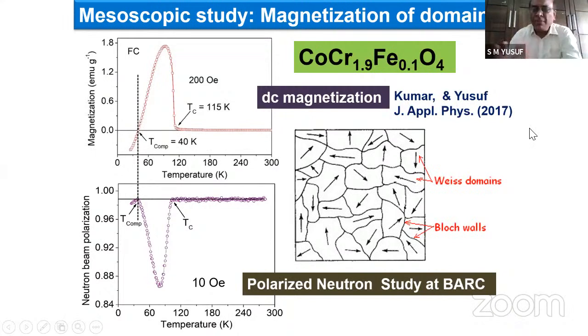That means magnetization is a bulk technique. Now we get magnetization, as you know, from the entire sample. You have taken 100 milligrams of sample. So you do not know at what level this cancellation is taking place. But net moment is 0 in terms of DC magnetization. But this neutron depolarization study is at a mesoscopic length scale, which looks at the magnetization at the domain length scale, domain by domain. So it tells you that at this temperature, each and every individual domain has got 0 net magnetization. That means the domain has lost its magnetization at this temperature.